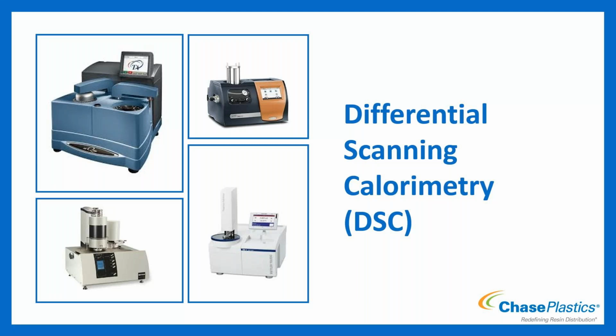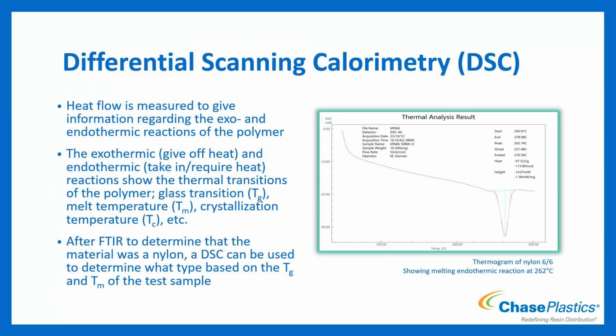So DSC, it's using heat flow, or heat flow is measured, and it gives us information regarding the exothermic and endothermic reactions within a polymer. So the exothermic, meaning give off heat, and the endothermic, meaning it takes in or requires heat for the reaction, it shows our thermal transitions within the material. So when we talk about glass transition temperature in both your amorphous and semicrystalline materials, being when the molecules can start to move a little bit, it shows that as a peak. Then you have your melt temperature for semicrystalline materials, so TM.